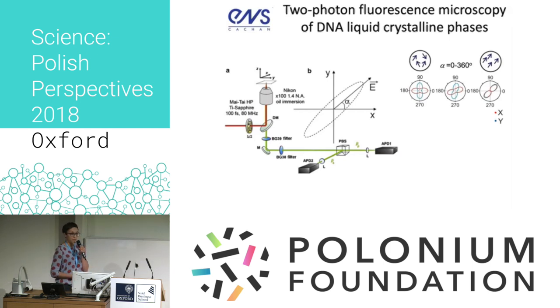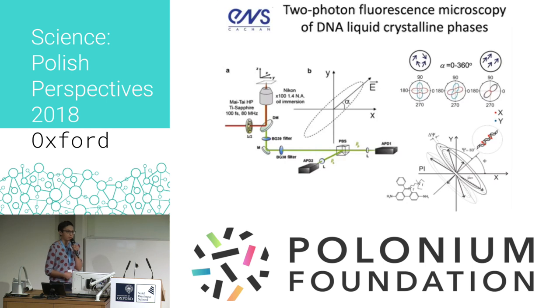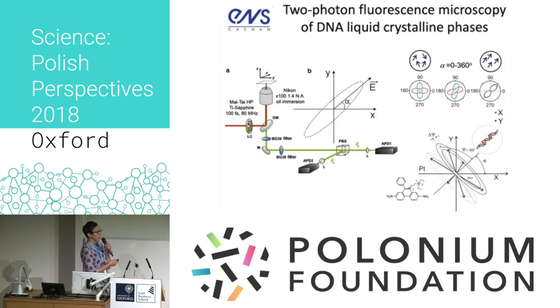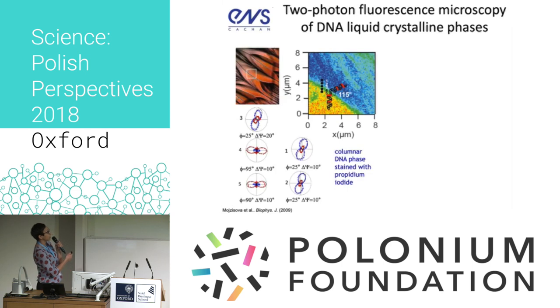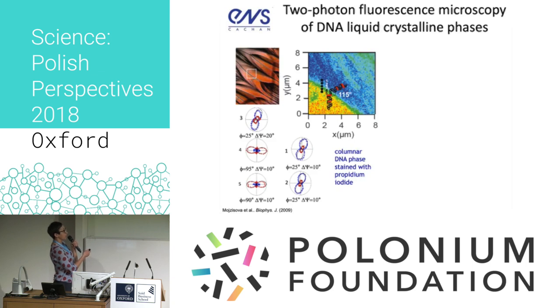We do that to see how fluorophores are organized in the sample. If we have an isotropic sample, the X and Y components are perpendicular to each other. But if we have organized fluorophores, X and Y components tend to align in the direction corresponding to the emitting dipoles. I used fluorophores with well-known DNA binding modes — for example, propidium iodide, which is an intercalator that binds with DNA strands perpendicular to the long axis of DNA. So when we image the orientation of propidium iodide, we can tell what the orientation of DNA is. We performed such studies with DNA liquid crystal phases, scanning chosen areas and performing polarization analysis at well-defined points — truly seeing the orientation of DNA across different spots and across liquid crystal domain borders.